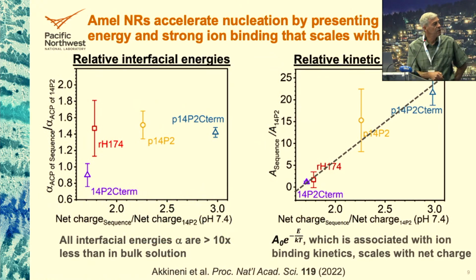Conclusion number 2 is if we look at the interfacial free energy, and here we've normalized it to the value of the 14P2 sequence, which is just the amelogenin fragment without phosphorylation. So that lies here at 1. What you see is that there's really not a lot of variation, but in addition to that, the interfacial free energies for the phosphorylated versions are actually higher than they are for the non-phosphorylated. They're all low. They're all very low compared to bulk solutions. So they all promote nucleation. But the phosphorylated versions are better, and not because the interfacial free energy is lower.